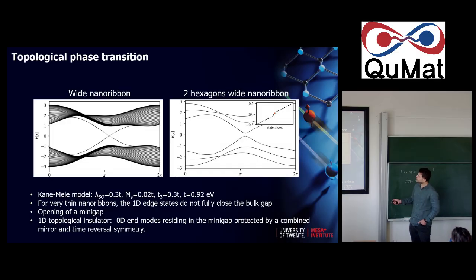And what you see is that for a wide nanoribbon, you have your edge states. But the moment you make it very narrow, over here is the edge state. You see that the edge state does not fully close the bulk gap, so it's gapped out. There is a gap, or a mini gap, that is forming at the edge state. And from the calculations, it can be seen that within that gap reside zero-dimensional states that are localized at the ends of the nanoribbon. And from the theory, you also expect that these zero-dimensional states are topologically protected by mirror and time reversal symmetries.